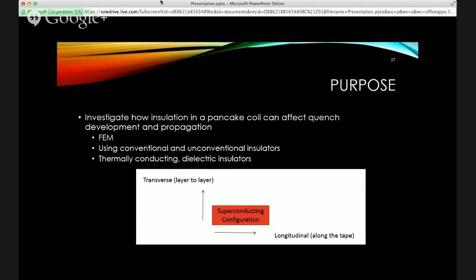So now on to what I did. I was looking at how insulation within a superconducting coil can actually affect that quench development and the propagation of that quench. So I'm a computationalist. Everything I've done has been on a computer. So I use finite element modeling or FEM or FEA, same type of thing. And actually looked at using the conventional insulator, which is currently used in multiple coils and different things in operation, and then also looking at using unconventional insulators, which are to get us to think outside of the box. An idea was if you now use an insulation that is thermally conducting but still electrically insulating or dielectric, then how would that affect how a quench manifests within the superconducting coil?